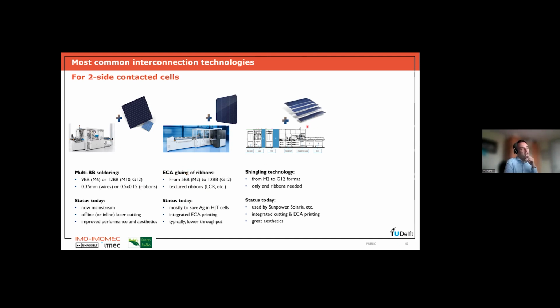Another approach, which is completely different, is so-called shingling. In shingling, we cut the cell into elongated strips, and then the interconnection is not done via these copper ribbons, but it's done like the shingles on a roof. So we connect one shingle on the side with the next shingle. You have a small overlap of 1 millimeter, let's say, between neighboring shingles. And this leads to very close packing, and also to a much better look. So the aesthetics are better. For instance, for building integrated applications, this is really nice.